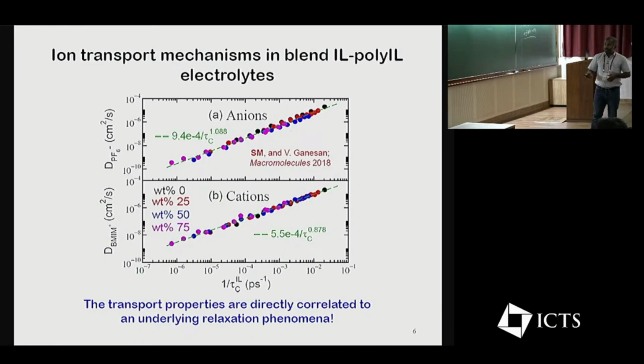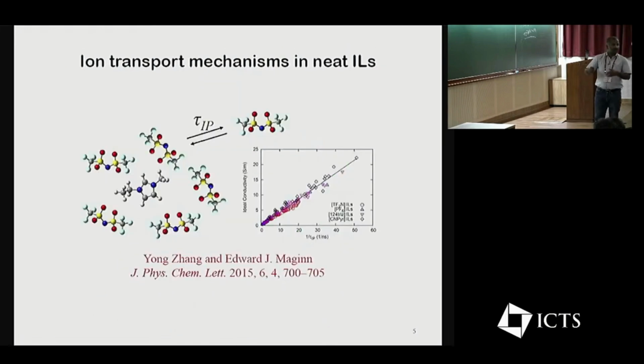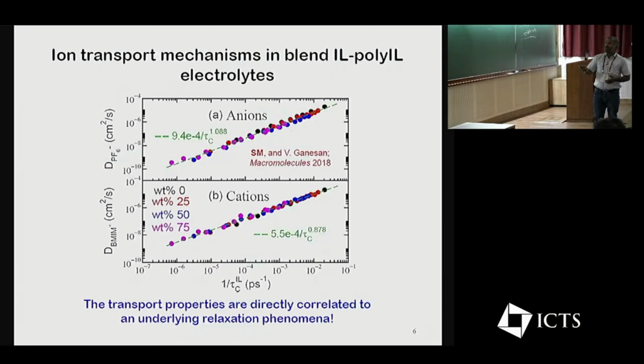After that, in a series of papers we have also demonstrated such a relationship between the diffusion coefficient and a particular relaxation phenomenon in a variety of electrolytes. Here it is a blend electrolyte. The previous one was for neat, that means pure ionic liquid electrolytes. And here we are trying to show it for a blend of liquid and a polymer electrolyte.